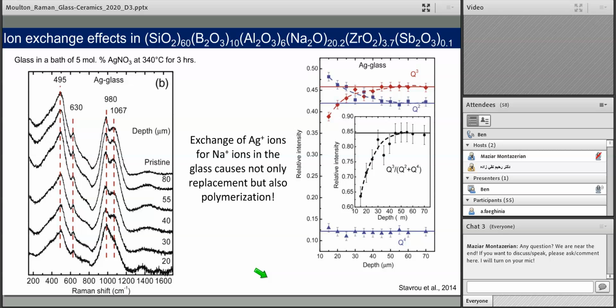Another great example of broad interest is ion substitution glass. For example, that which produces the strong screens on your phones. In this very complicated, but ultimately another sodium silicate glass with a bit of boron, aluminum, zirconium, and antimony mixed in, when they left it in the silver nitrate bath, they showed that as you go into the sample, this peak at 980 decreases and the peak at 1067 increases. So they show that not only are there tensile stresses building up in the surface of the glass, but you're actually changing the structure. And as the silver content increases towards the surface here on the left-hand side of this graph, you have less Q3 and more Q2 forming. This is guaranteed to change the properties of the glass and ultimately its strength.